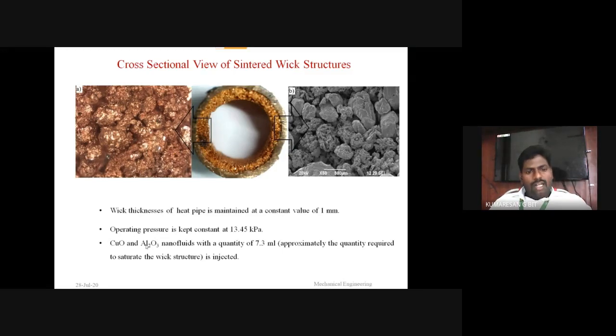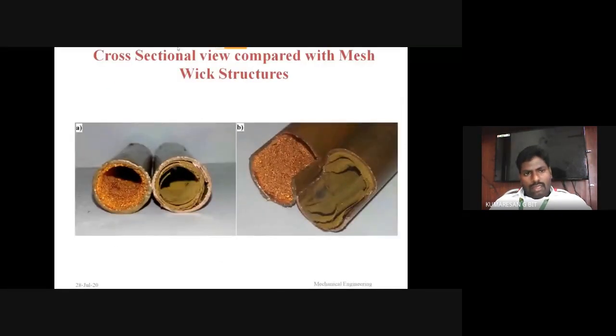Then copper oxide and aluminum oxide nanofluids with a quantity of 7.3 ml. This quantity is approximately equal to what is needed to saturate the entire wick structure present inside the heat pipe. It is injected into the heat pipe at the time of fluid filling. Then the cross-sectional view of the sintered and mesh wick structures is given here.